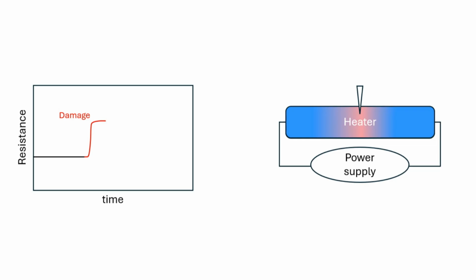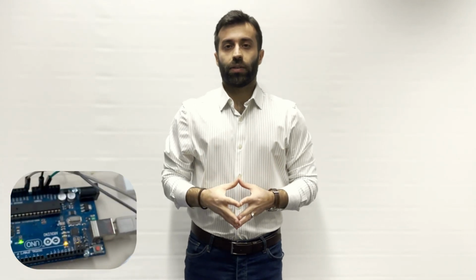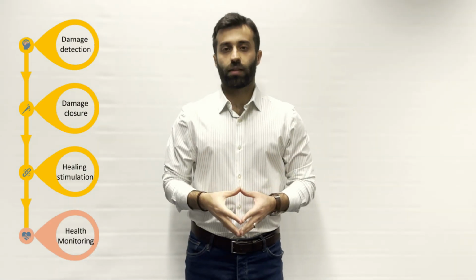If the system has healed properly, the resistance should return to its initial value, or the heat distribution should be uniform rather than concentrated at a specific location. This means that by monitoring the resistance of an electrically conductive self-healing material or analyzing the temperature distribution, the robot can gain information about its own health as one of the final self-healing phases. Health monitoring has different aspects. One can be the recovery of the material fracture properties, and another one, the recovery of the material or the robot's mechanical stiffness. As for healing, temperature increase is often necessary. This causes the material to be softer. And in many cases, it takes several hours until the material or the robot recovers its initial stiffness. This long recovery is of course not acceptable for many applications.